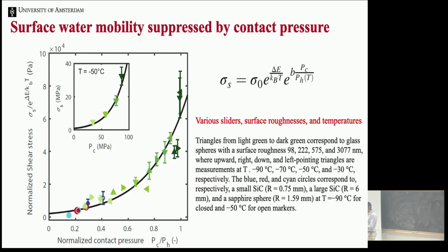What happens now if I press on the surface is that I will hinder the mobility of these molecules, and I have to correct for that. And A.Huerre, who dropped off my slide, proposed that that is actually a correction to the activation energy. Yeah, so my activation energy gives the difficulty or easiness for the molecules to move. And if I confine them, I actually increase this activation energy to an effective interaction energy.